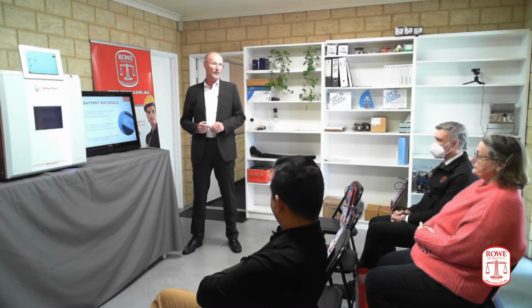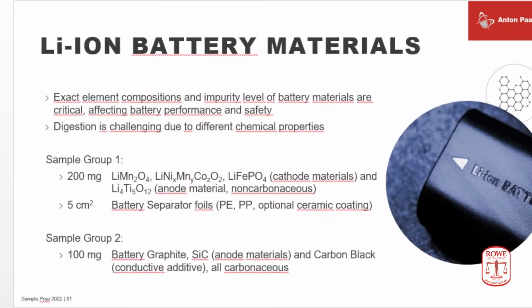When we look at lithium-ion battery materials, there are many. They are mostly lithium minerals with manganese, with cobalt, with iron, and they are used in their purified form as cathode materials in the lithium-ion batteries. We also can, for instance, analyze battery separator foils, which are used in battery manufacturing to separate anode from cathode substances. They're mainly based on polyethylene or polypropylene, sometimes with ceramic coating. So you can imagine this combination of elements that's quite difficult to get destroyed completely. So the acid mixture to do this must be well chosen according to the nature of the individual sample material.